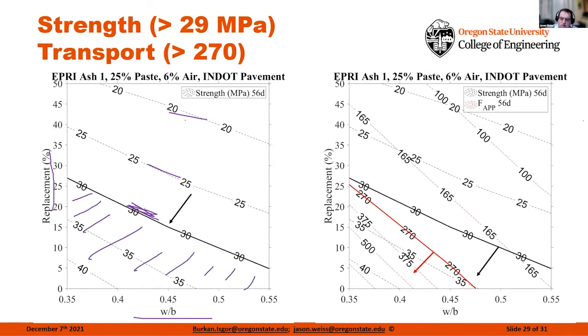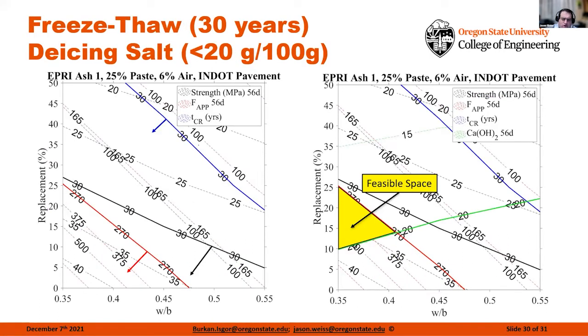I can do the same thing when I start to look at the transport properties, and now everything below this red line is something that's worth manufacturing. I can continue this over and look at freeze-thaw performance, which is everything below the blue line. And then if I look at the calcium hydroxide, it's actually everything above this green line. So what this really helps me to do now is I've considered a huge range of potential mix designs, but I've been able to focus in on the region that makes the most sense and the likeliest set of mixture proportions that are going to meet my specific design criteria.